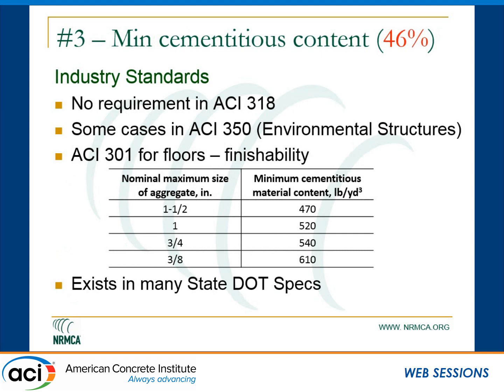Minimum cement content. We really don't have any restrictions for minimum cement content in our standards. There's nothing in ACI 318. There are some cases in ACI 350 for environmental structures. And for floors, you can see that the minimum cement content to get enough paste is relatively low, but there's an out to that. If you can do a mock-up and actually evaluate a test slab, you can use less than the minimum cement content.